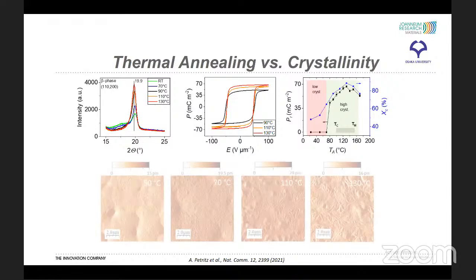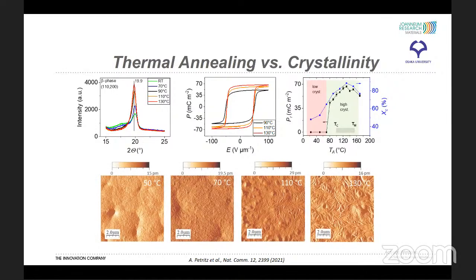The change in crystallinity is also reflected in the morphology of the layer characterized by AFM. With higher annealing temperatures, the lamella-like crystallites grow in intensity and size, as you can see here.